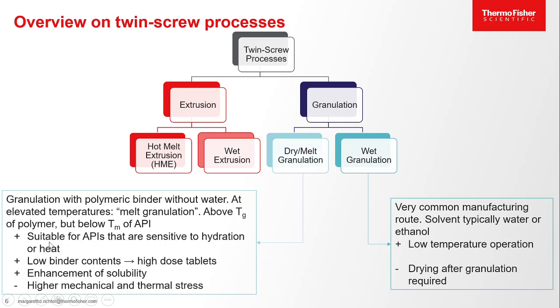This is a very nice process because it's suitable for active ingredients that are sensitive to hydration and also to heat, because the residence time during the granulation process is quite short. So also the residence time at elevated temperatures is short. Then you can work with quite low binder contents, so high dose tablets are possible. And you can enhance solubility if you work with a solubilizing agent, so the polymer can have some solubilizing effect as well.